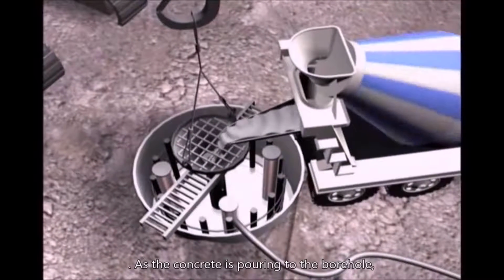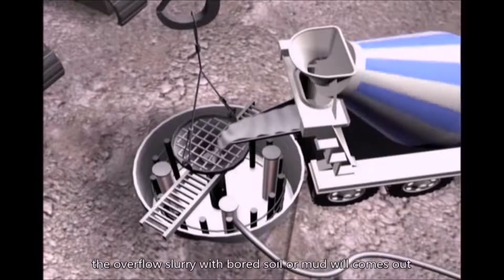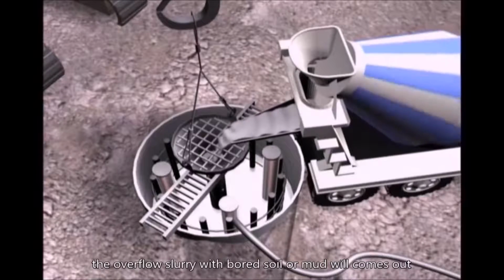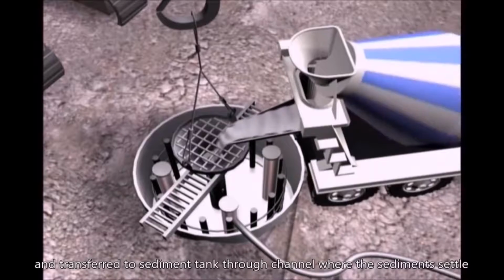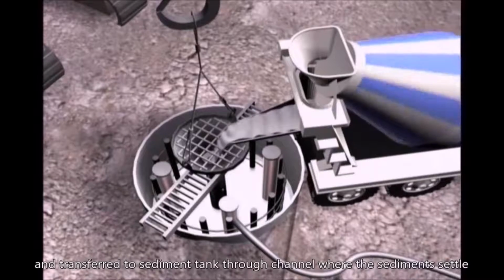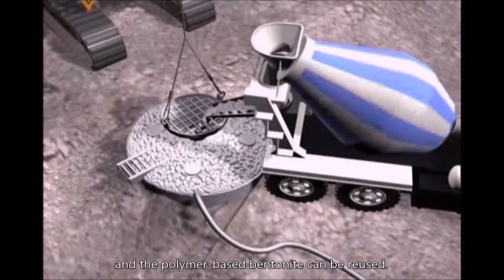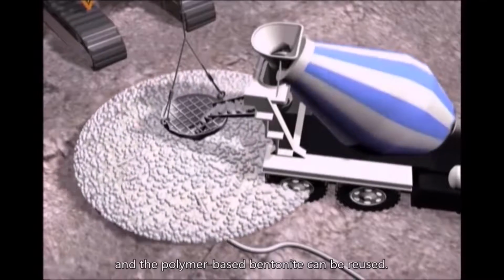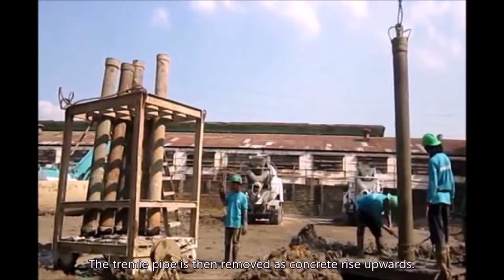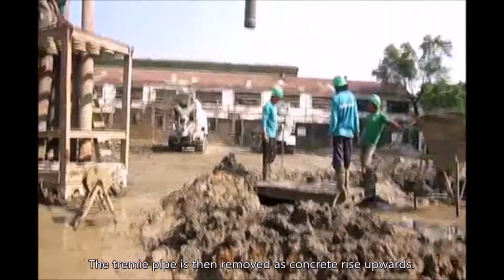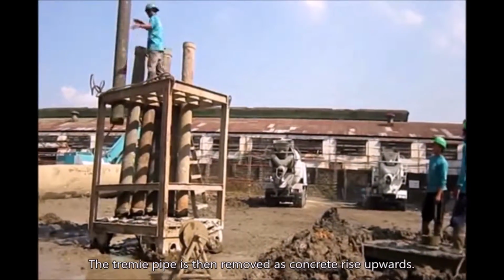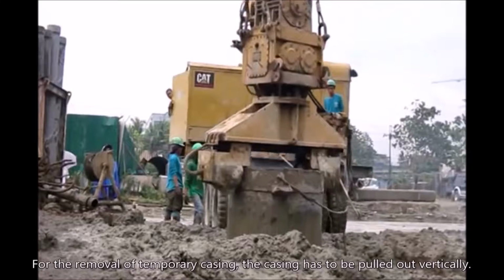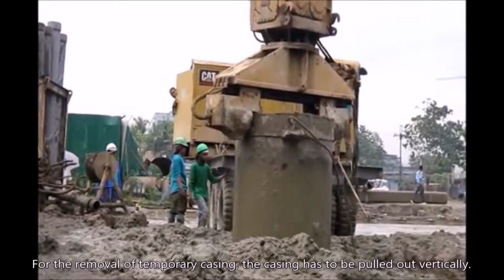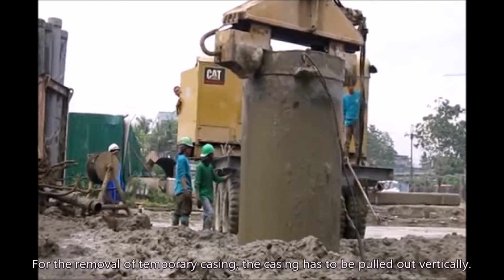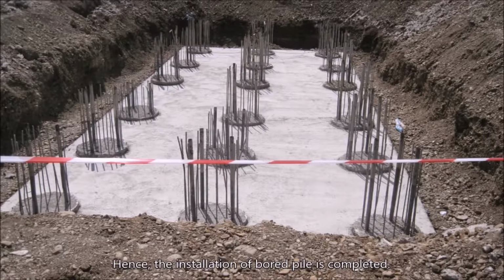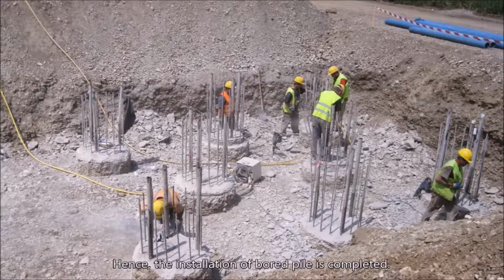As the concrete is poured into the borehole, the overflow slurry with bored soil or mud will come out and be transferred to a sediment tank through a channel, where the sediment settles and the polymer-based bentonite can be reused. The tremie pipe is then removed as the concrete rises upwards. For the removal of the temporary casing, the casing has to be pulled out vertically. Hence, the installation of the bored pile is completed.